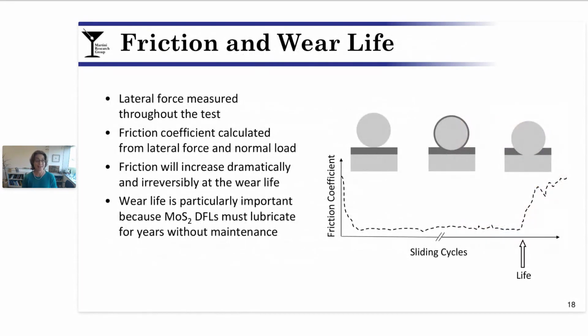So what do you get out of this? Shown on the right here is an artist's rendition of a friction coefficient versus sliding cycles plot. You measure lateral force, you calculate friction coefficient, and it looks something like this. You see a rapid decrease right at the beginning of the test. This is associated with run-in. Then you see a long, steady state, low friction period. This is the majority of the operation of the mechanical system.